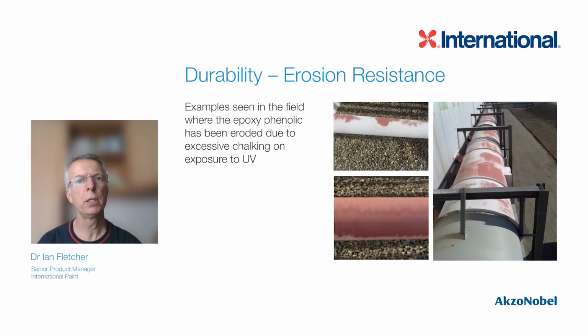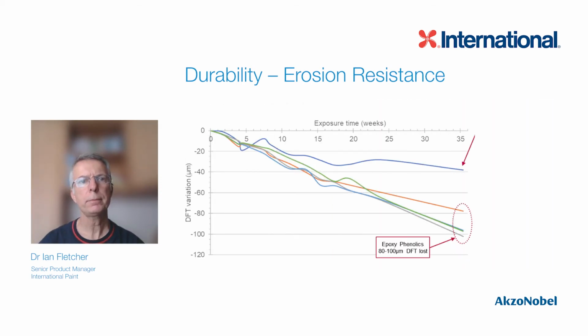2340 UPC also has enhanced erosion resistance. Typically, epoxy phenolic schemes are specified without a durable top coat. As a result, when used in uninsulated service, there have been examples seen in the field where the epoxy phenolic coating has been eroded, reducing the dry film thickness and leading to poor corrosion protection. In accelerated erosion testing, Interbond 2340 UPC has been shown to far outperform traditional epoxy phenolics, losing considerably less coating thickness over the same time period.